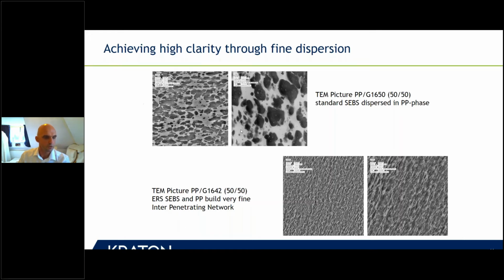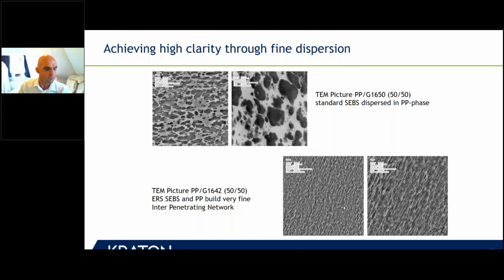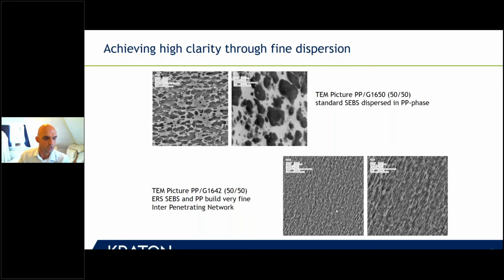So these are two examples. The top one is a G1650 with polypropylene, a 50-50 mix, and it's showing basically dark stained are the polystyrene domains. So it's showing the size of the domains of the polystyrene. So these are polystyrene-rich domains. So you see that they are pretty coarse. Now, if you take a G1642, which is an ERS grade polymer, you see that there's a much finer network here, much finer interpenetrating network. This is, of course, good news.